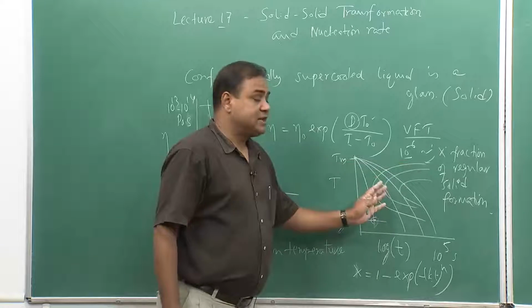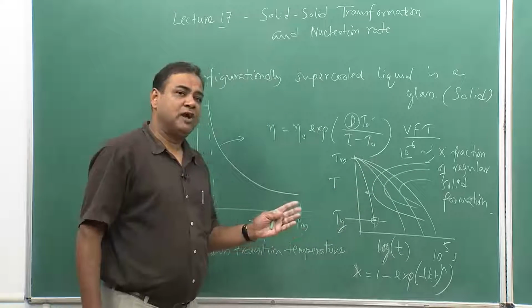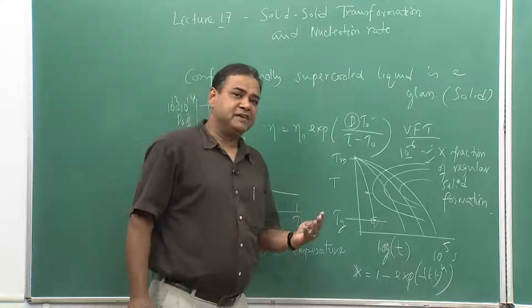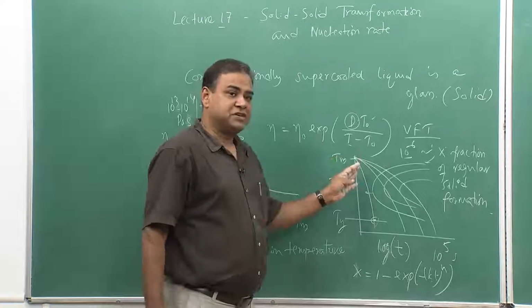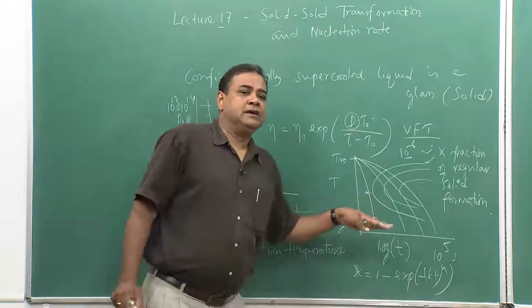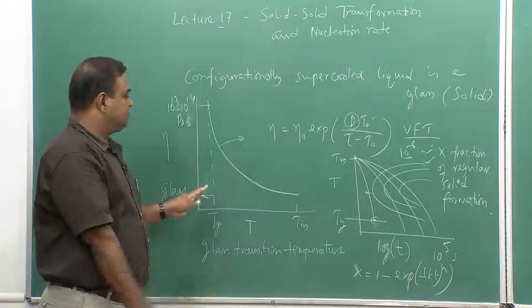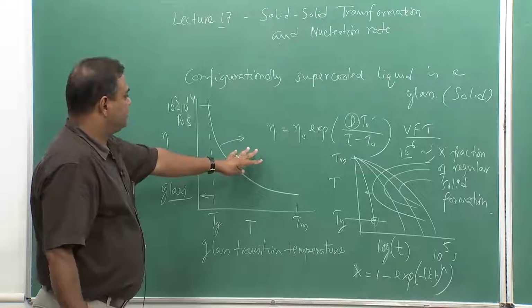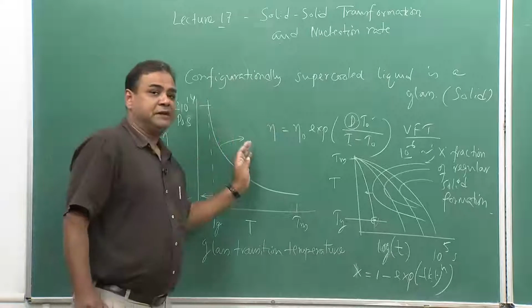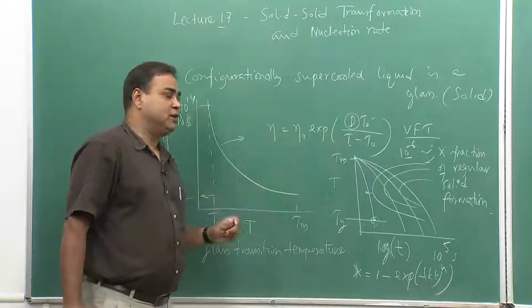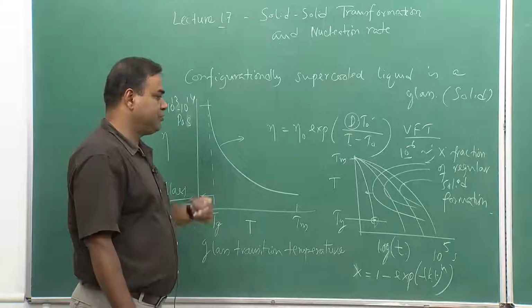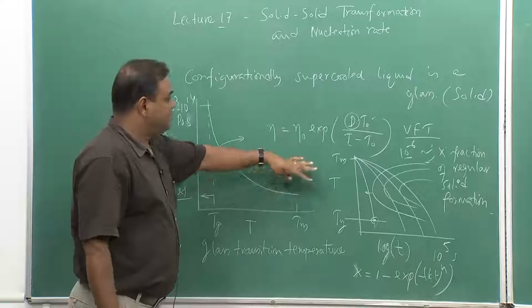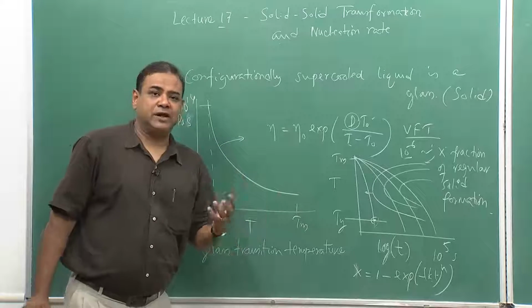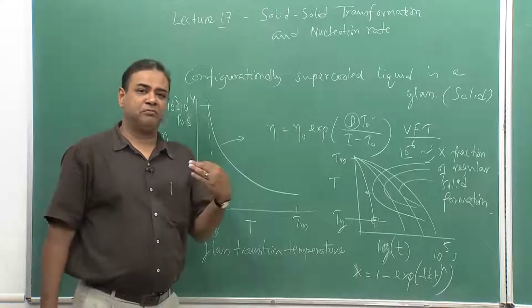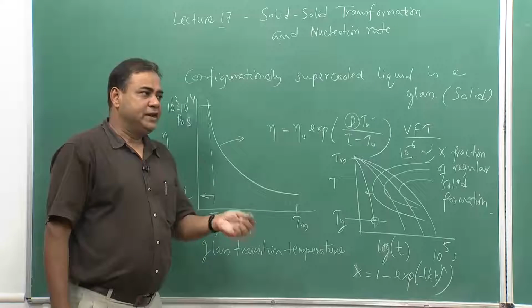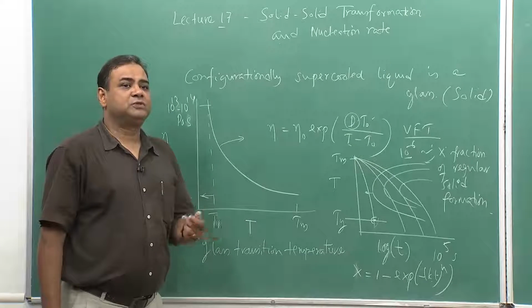And this TTT diagram will be valid while finding the kinetics of phase transformation from liquid to solid. So this is a kind of use of that I measurement. Of course, the growth rate we will start looking at soon. Finally, we can see whether the liquid can form glass or not, or it can form some crystal, and when it should form the crystal, what would be the critical cooling rate.